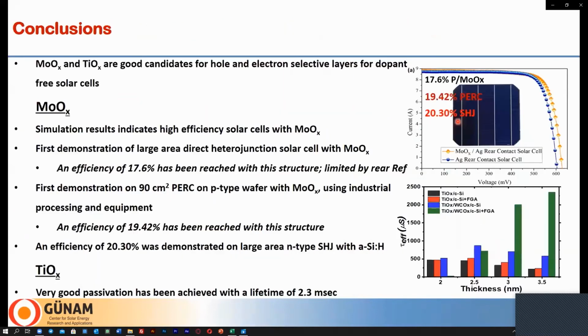So finally, I come to the conclusion. Molybdenum oxide and titanium dioxide are good candidates as hole selective and electron selective layers in dopant-free and passivating contact solar cells. Our simulation showed that high efficiency is possible with molybdenum oxide, and as we will see later today from other presenters, titanium dioxide also shows high efficiency. We have also demonstrated a large area direct heterojunction of P-type silicon and molybdenum oxide with efficiency exceeding 17%.